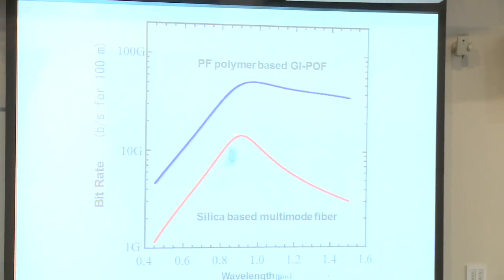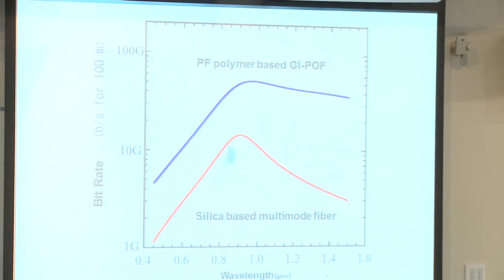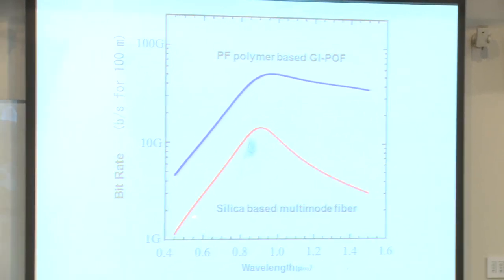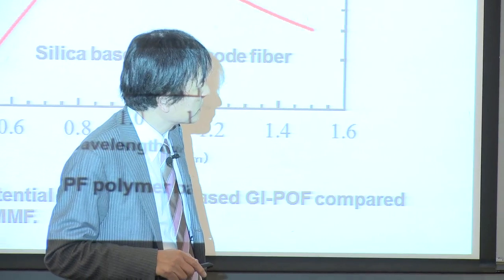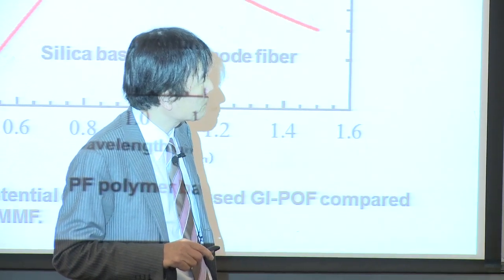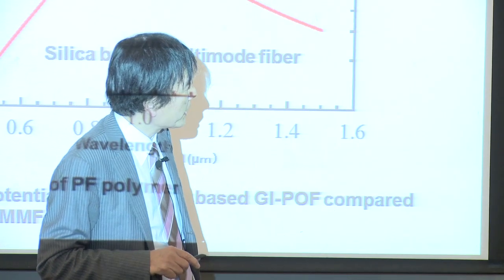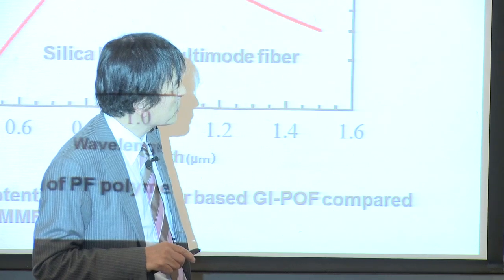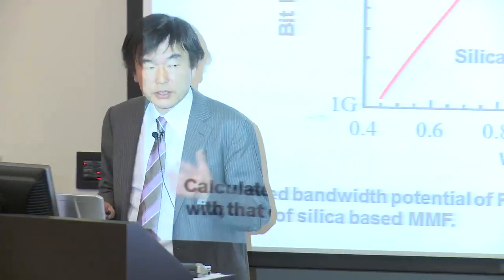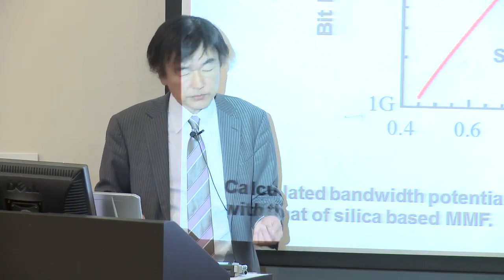Silica multimode fiber can cover 10 gigabit per second. But if the wavelength of the laser is 0.6 or 1.5 microns, then that bitrate is seriously deteriorated. But in the case of the perfluorinated polymer-based GIPOF, the bitrate from the visible to 1.5 microns is almost on the order of 40 gigabit per second. That is due to the material dispersion. So this is an inherent characteristic.